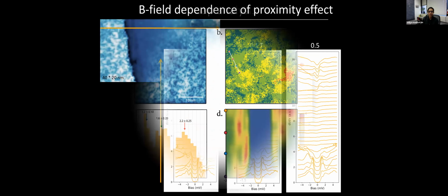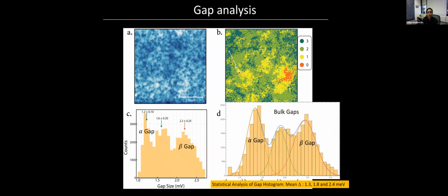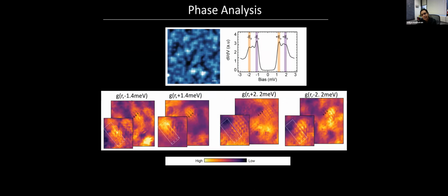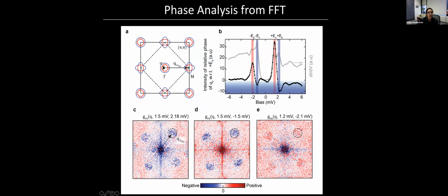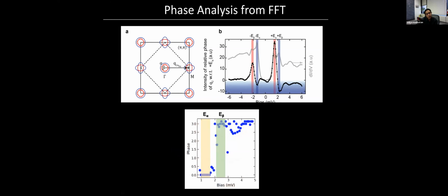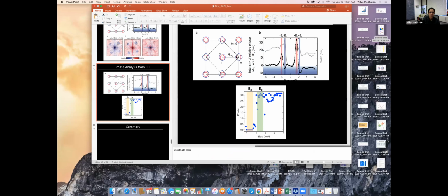But in the interest of time, I'm going to skip over all this and just show you one interesting thing, which is that with STM, you can do a phase analysis and ask the question, what is the relative phase of the order parameter in these various pockets? By doing this phase analysis, what we found is that not only is there a phase shift between the hole pockets and the electron pockets, but there's also a relative phase shift between the two hole pockets at the gamma point, which is very much in line with Jiangping Hu's prediction. Okay, I'm going to just stop here because I think I've run out of time. Thank you for your attention.